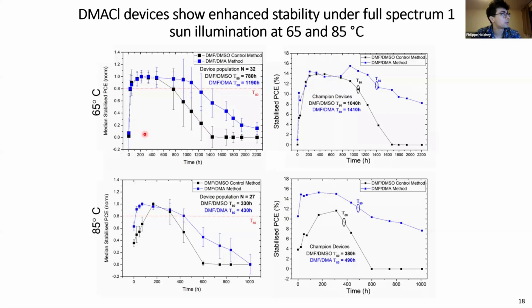And here we see that we have quite a large number of devices. And the DMF-DMA devices have a T80 of 1,200 hours roughly at 65 degrees. And the controls roughly around 780 hours in the same conditions. And at 85 degrees, we see a lower lifetime, which we find to be quite usual. And there the T80 time for the DMF-DMA device is roughly 430 hours. And here on the right, you see the champion devices.